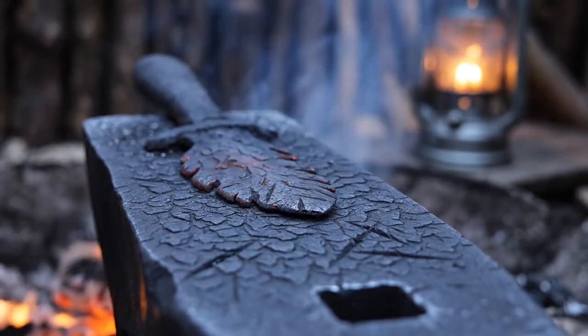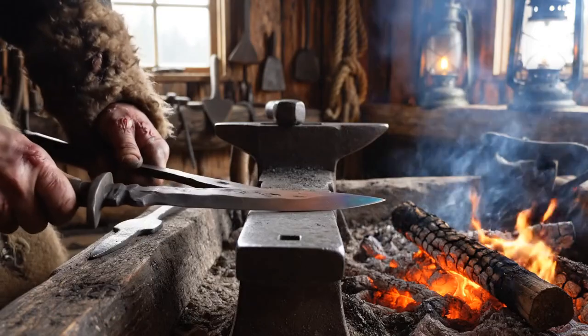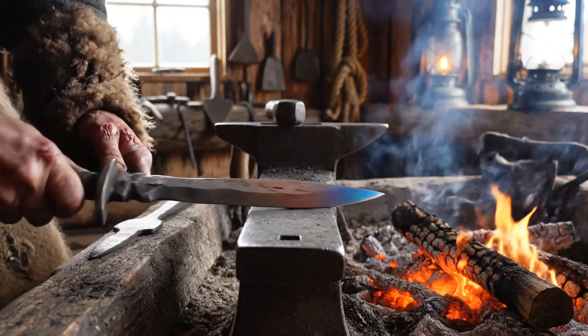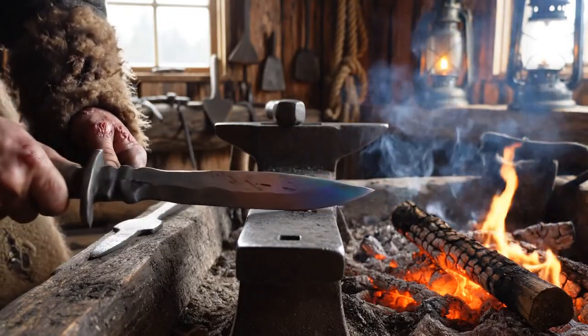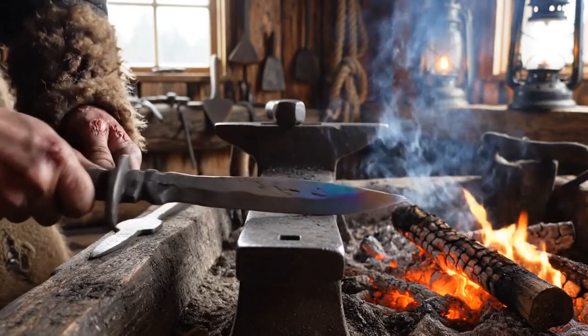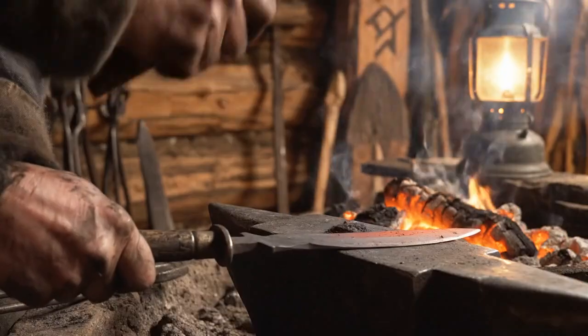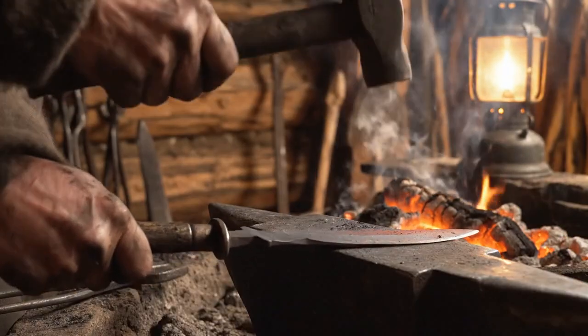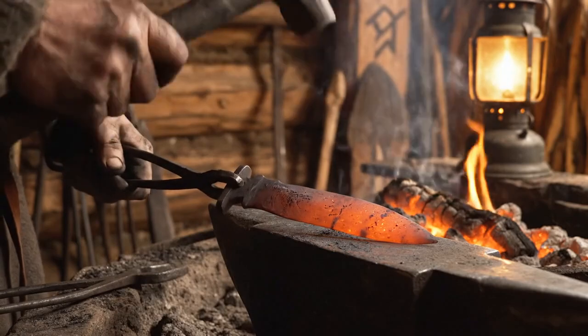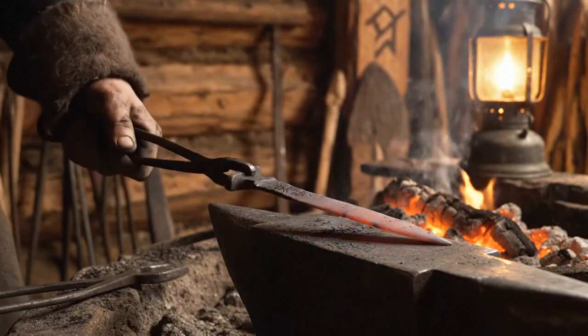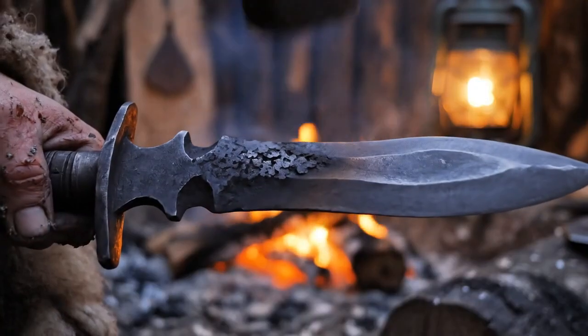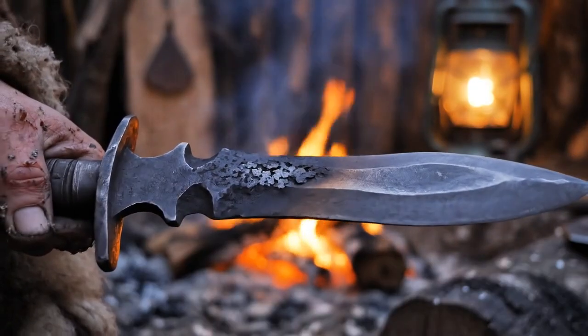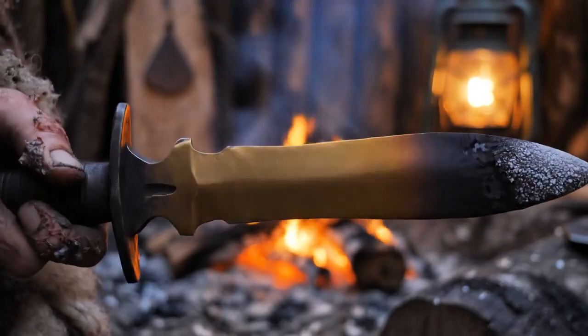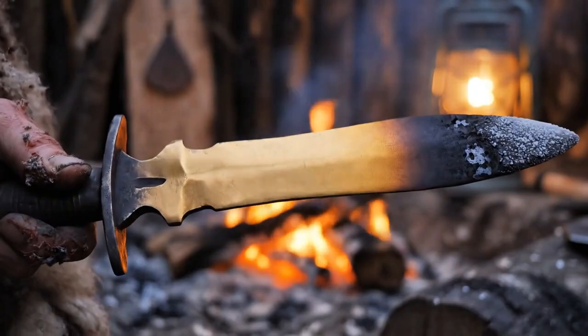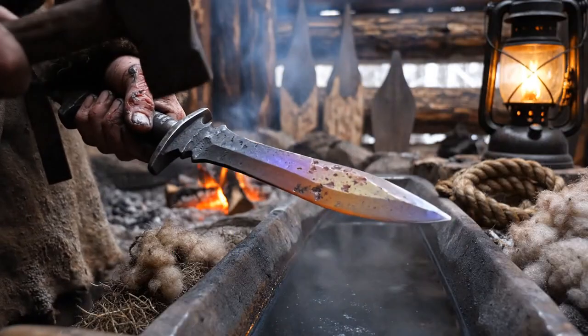When iron heats up, its surface forms a thin layer of iron oxide. Picture the way a cast iron pan turns a slightly gray-blue color when it gets truly hot on the stove. That layer is porous at the microscopic level, like a sponge with openings too small to see but large enough to matter. When raw linseed oil touches that hot, porous layer, the heat breaks the oil down into smaller molecular chains. Those chains flow into the pores, then they polymerize. They lock together inside the metal's surface the way resin hardens inside wood grain when it cures.